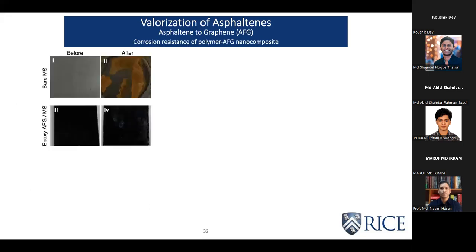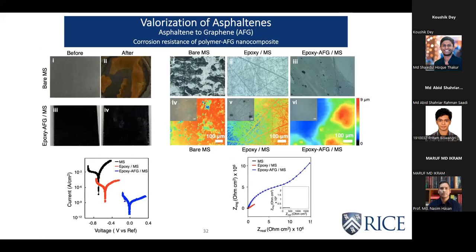After the thermal properties, we also tested some functional properties, and these were done by our collaborators. I'm not going to talk much about it, but basically we applied this composite as a coating on steel substrates, and we also saw good corrosion resistance properties. Polymers are often used as a corrosion resistant coating to protect metals and alloys, but here we show that if we reinforce those polymers with a little bit of AFG, or asphaltene-derived flash graphene, the performance can be even improved. We also did some quantification. Again, I'm not going to talk much about this particular thing.